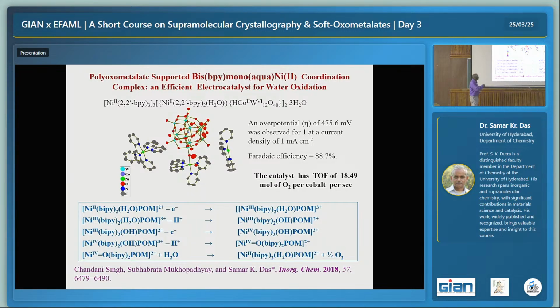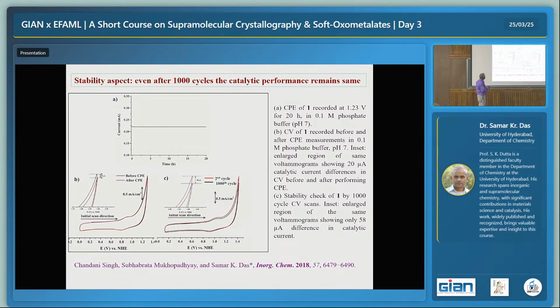It will give a continuous cyclic manner. It will give bubbling of oxygen. And again, we got very interesting parameters like what we wanted to have: Faradaic efficiency close to 90%, very good turnover frequency, and decent overpotential. You can make it cycle. We also did the CPE and cyclic stability to 1000 cycles. It is almost the same, a little bit different because of vigorous oxygen gas coming out. Some may come out, just a little bit of decrease.